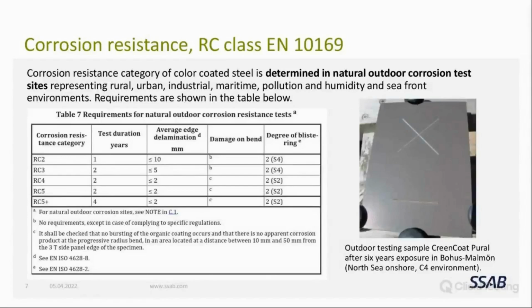For example, demanding for RC2 category is 1 year test period, and its delamination maximum 10 millimeters, and degree of blistering density 2 and size 4. And there are a certain visual standard how to estimate these blister size and blister densities. Then the demanding for this RC5 plus class is 4 years test period, delamination maximum 2 millimeters, and degree of blistering density 2 size 2.